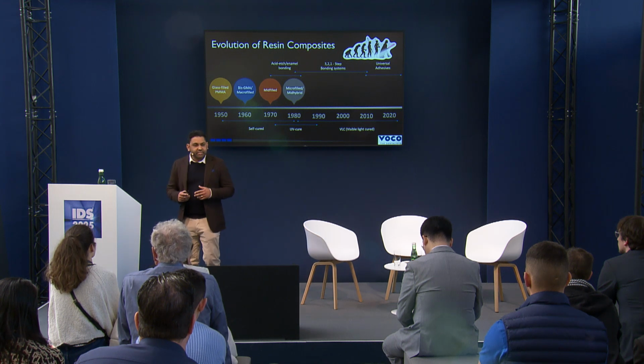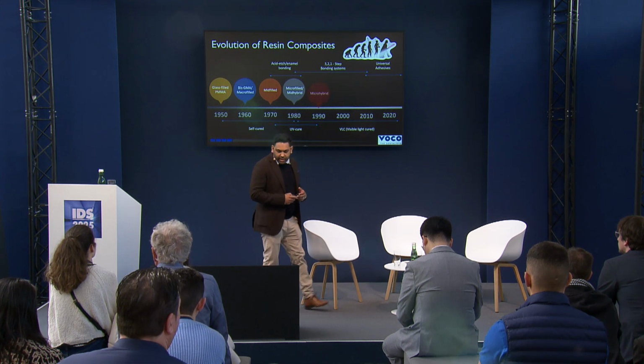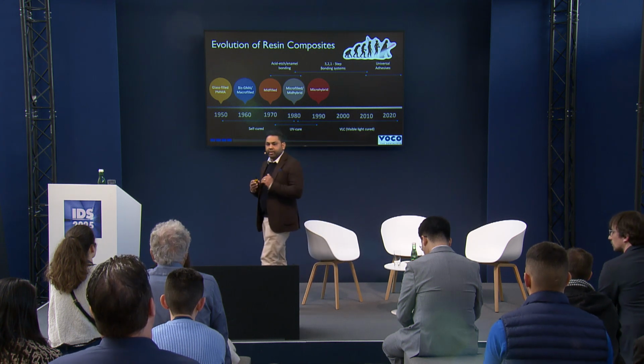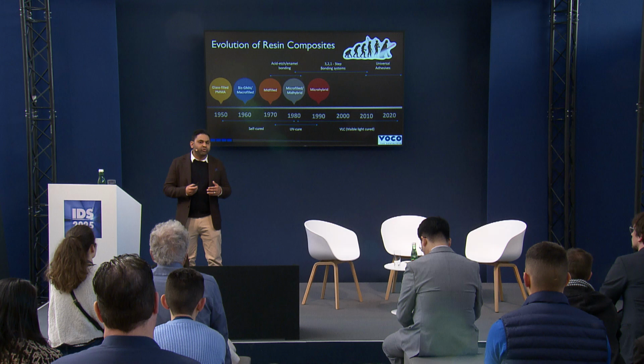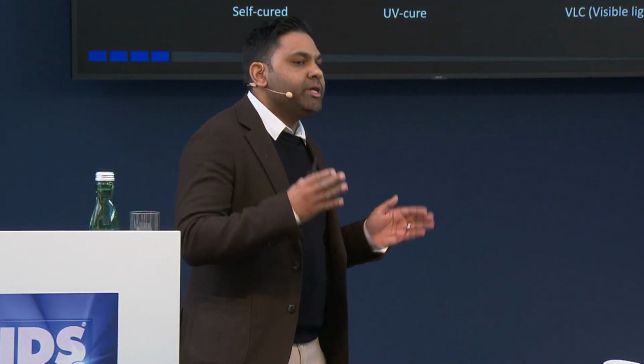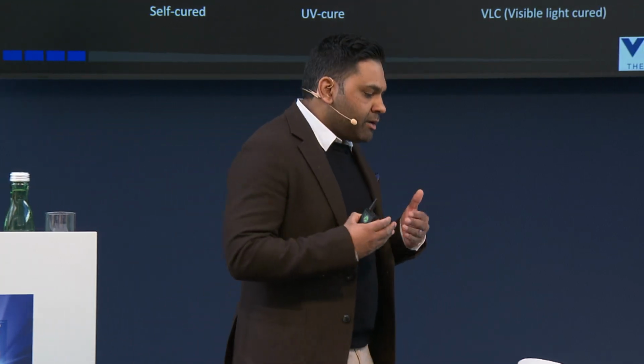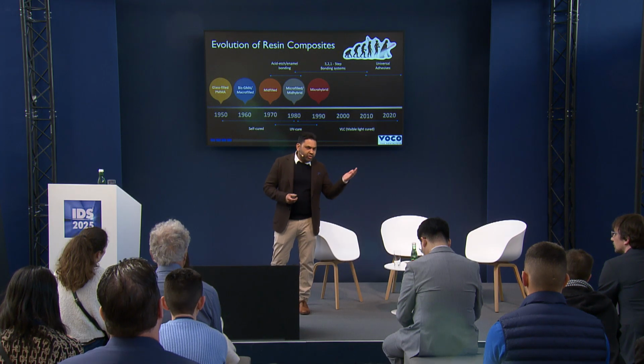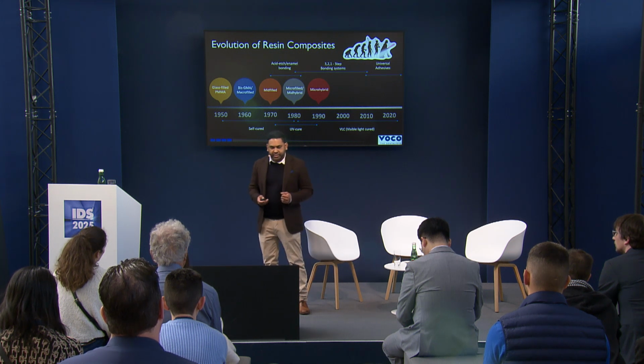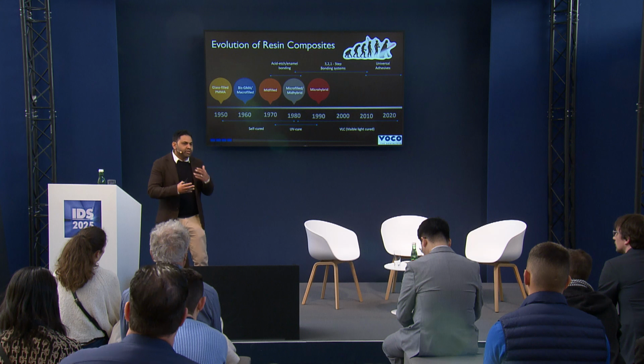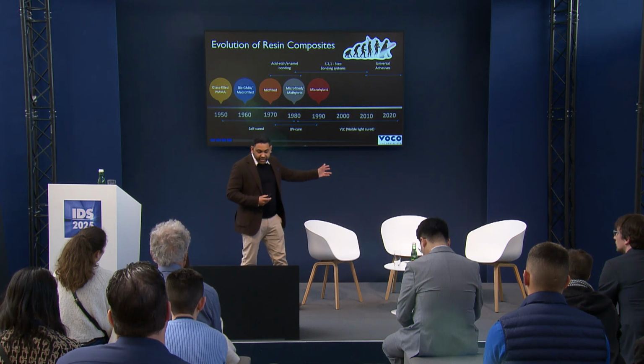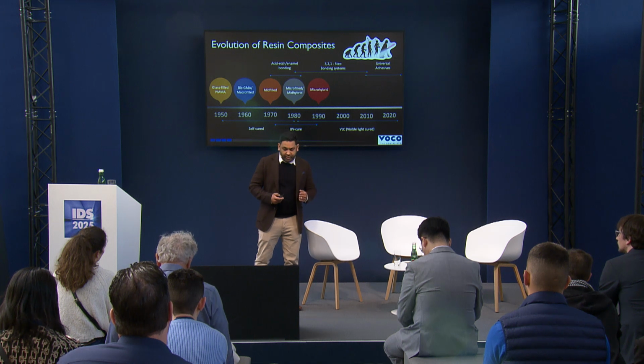But the demands of patients and practitioners also began to grow. And this was the birth of a hybrid material. The concept of having a universal material has been something that we've recognized for some time. And actually, the way that we were able to do this is by having a mixture of filler particle sizes between less than 2 microns and 0.04 microns. So we also started to see a more traditional chemistry that we see these days, which is a combination of the inorganic filler and the resin matrix, as well as the initiator molecule to set off the polymerization reaction. And here we can see much more established visible light curing.